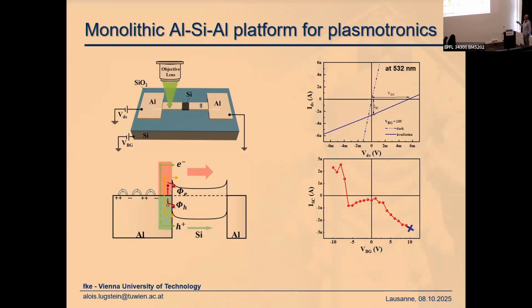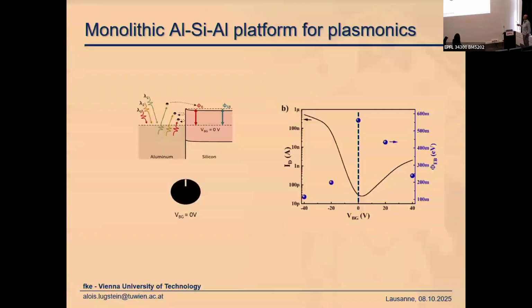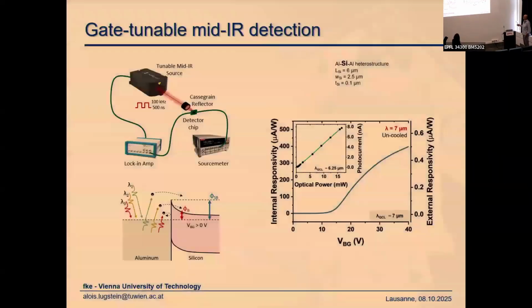Sure. For the green laser, the energy of the electrons is somewhere here. So you cannot block them completely. The point where you get zero current is the point where you inject the same amount of holes and electrons. When you assume you have flat band, then you inject the same amount of holes and electrons, you have zero current, but you still inject, so the plasmons decay. When you do these experiments with light with an energy less than the barrier height, and this is shown for the 7 micrometer, then you can really completely block the current and you inject no charge carriers.